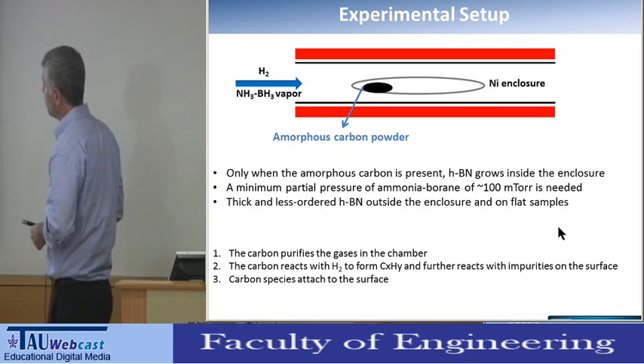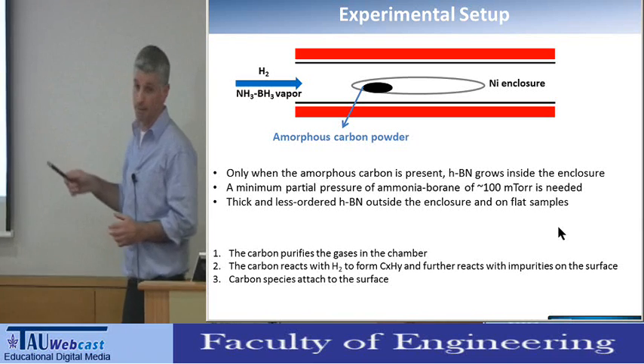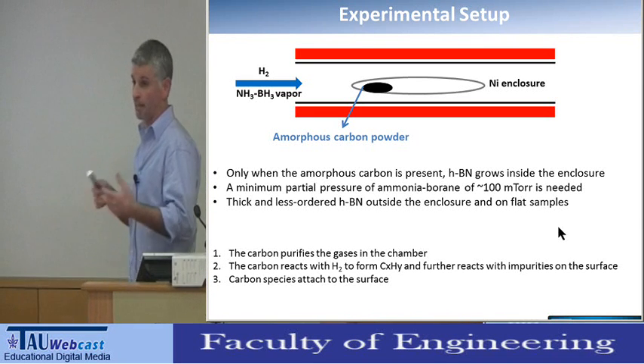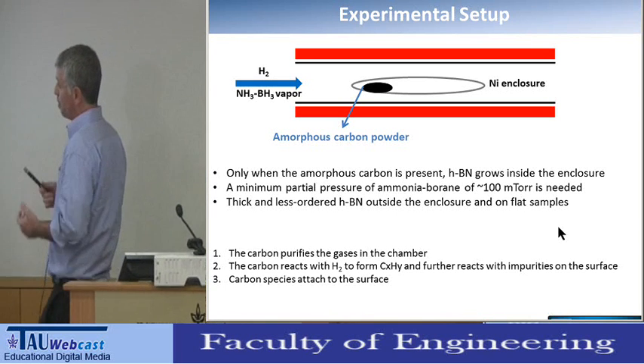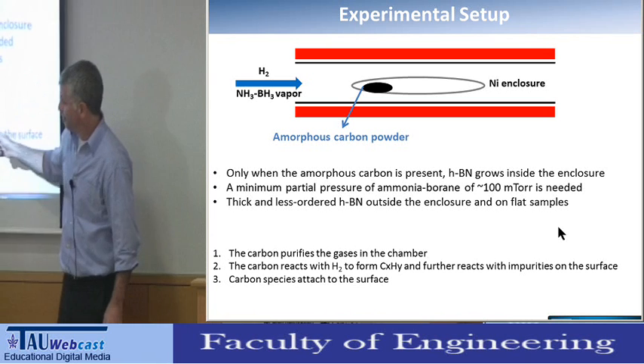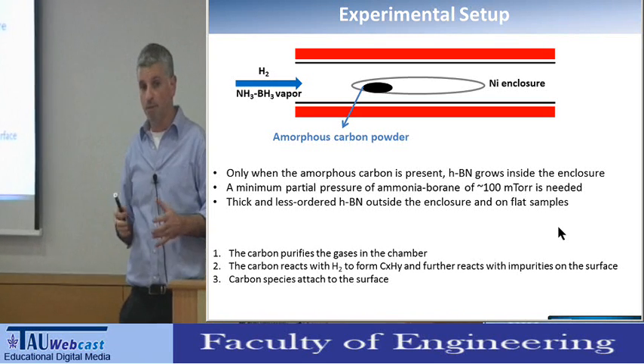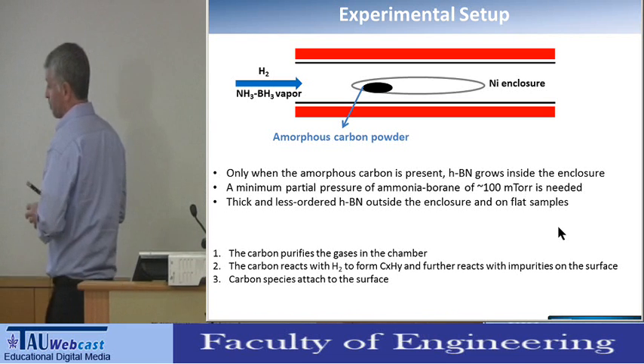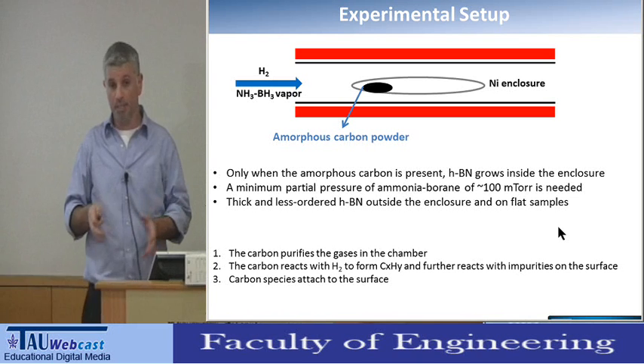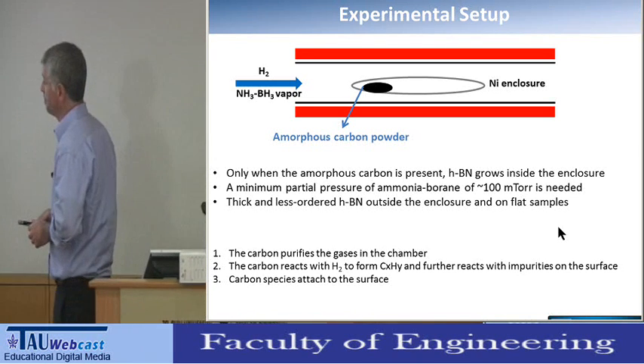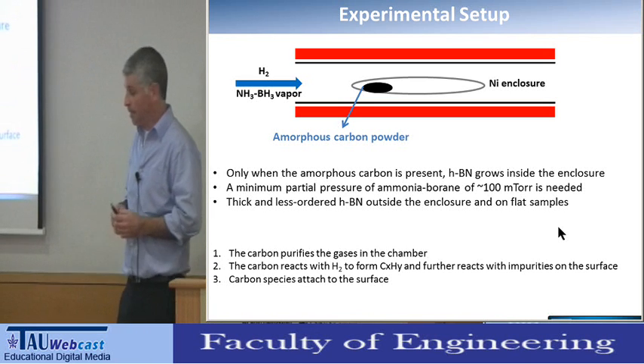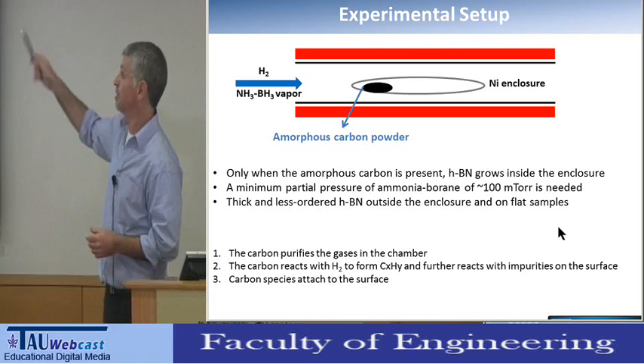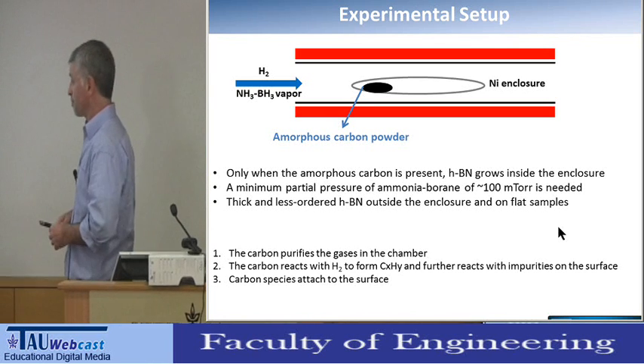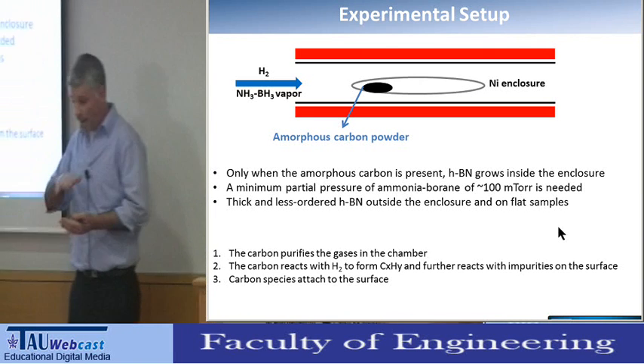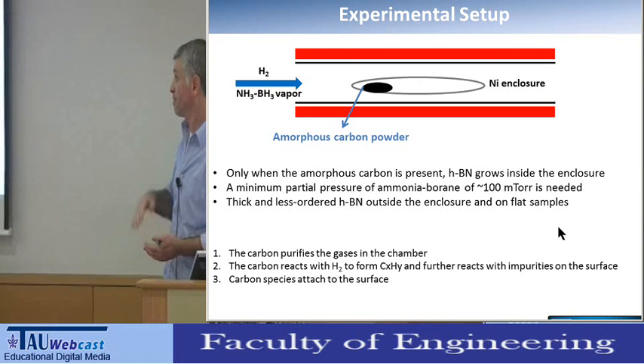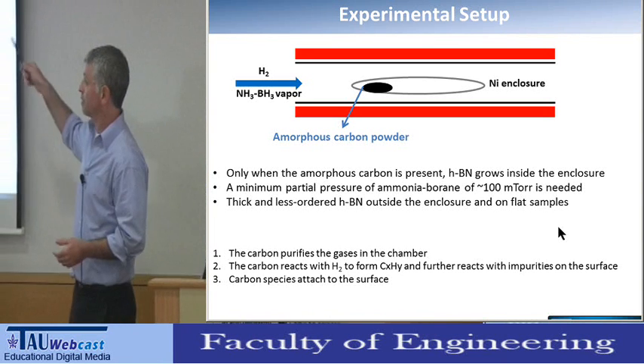So the reasons for the growth of HBN so nicely inside the pocket. By the way, outside the pocket we get only thick and disordered HBN. Inside the pocket, the reasons could be the following. One is that the amorphous carbon acts as a purifier of the gases coming into the chamber. We use ultra-high purity gases, but still they have some impurities in them. The second possible reason is that the carbon reacts with the hydrogen in the chamber at high temperature, and then the hydrocarbon reacts with oxides or other impurities on the surface, so it cleans the surface of the nickel, promoting the growth of HBN.